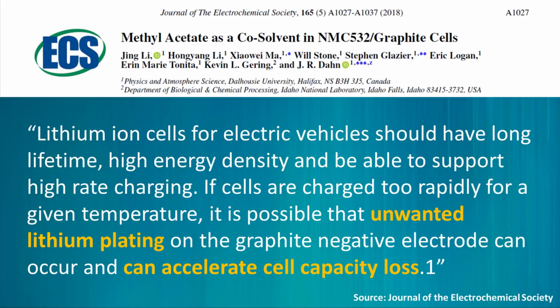Lithium-ion cells for electric vehicles should have long lifetime, high energy density, and be able to support high rate charging. If cells are charged too rapidly for a given temperature, it is possible that unwanted lithium plating on the graphite negative electrode can occur and can accelerate cell capacity loss. However, this research goes on to talk in great detail about how methyl acetate as a solvent can solve this problem and will lead to a battery that is able to have a high rate of charge yet not be damaged with as much lithium plating.